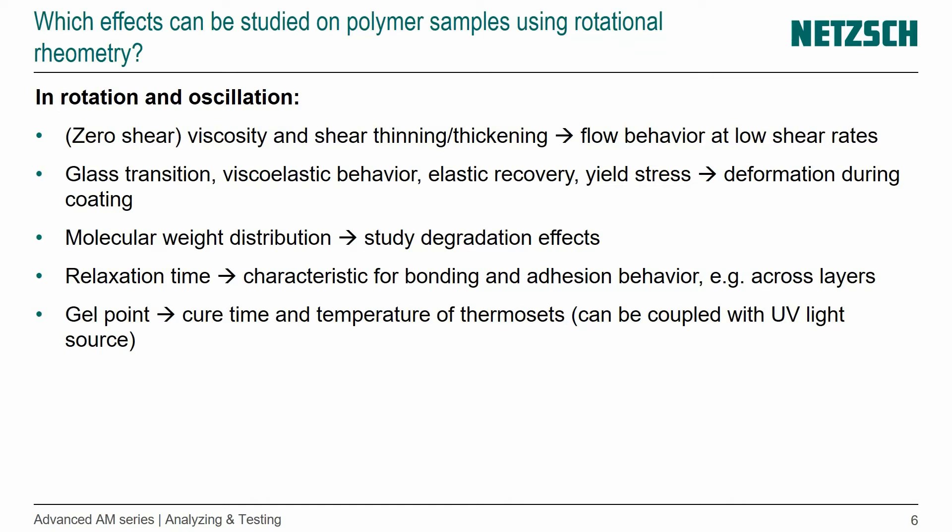And we can get the gel point. Another quantity that's important if we're dealing with thermosets that cure. The gel point tells us something about the cure time and temperature. And as we're talking mostly about UV curable resins, a rheometer can be coupled with the UV light source to actually obtain these values.